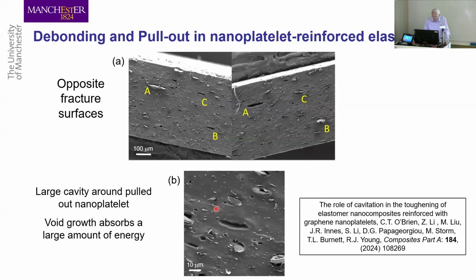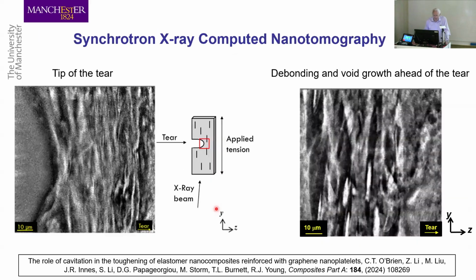So we've got these large cavities that form. And what we've done is actually observe this directly in the synchrotron. We've done synchrotron X-ray computed nanotomography. I've got a video of this on YouTube, but what you can do, you can look at the tip of a crack, tip of a tear, and you can see these graphene flakes sitting in great big cavities, these enormous cavities that form. And the energy required to form these cavities is enormous. So you're nucleating this cavitation in this particular case to get the toughening. But again, you don't have to have graphene to do that. Any 2D material probably could do that.